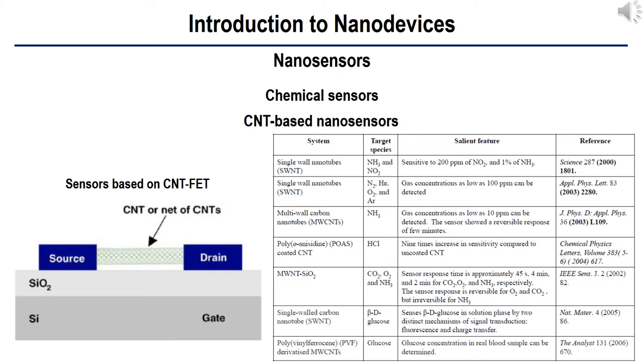Carbon nanotubes are advantageous in the fabrication of chemical nanosensors due to their exceptional properties. CNTs have a high length-to-radius ratio, allowing greater control over unidirectional material properties. They can behave as metallic, semiconducting, or insulating material depending on their diameter, chirality, and any functionalization or doping. They have a high degree of mechanical strength — greater than carbon fibers — and flexibility. Their properties can be altered by encapsulating metals inside them to make electrical or magnetic nanocables, or even gases, making them suitable for storing hydrogen or separating gases.